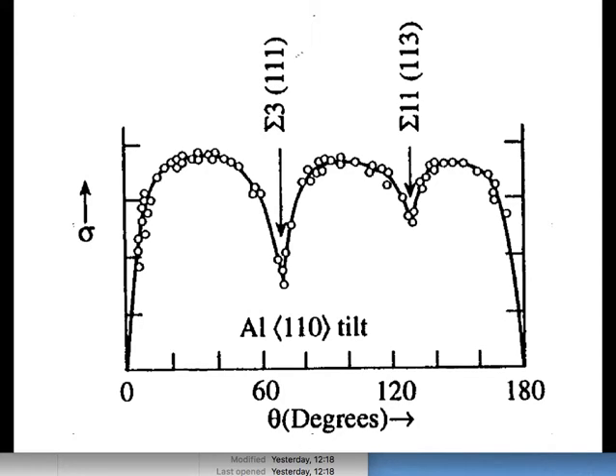When you get to very large values of sigma, they are not terribly meaningful, okay? Because a very small fraction of lattice points will be coincident. Okay, we can see that the angles here are quite large, all right? So the coincidence site lattice concept applies beyond small angles. So you can think about this as the Read equation up to here, okay?